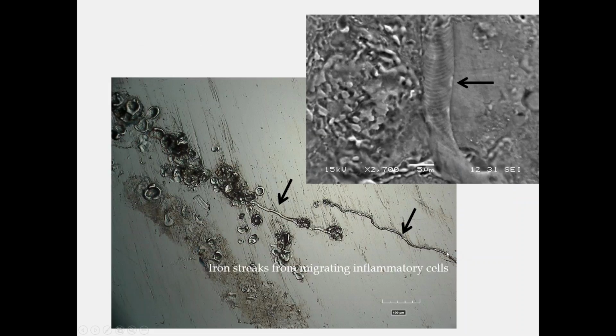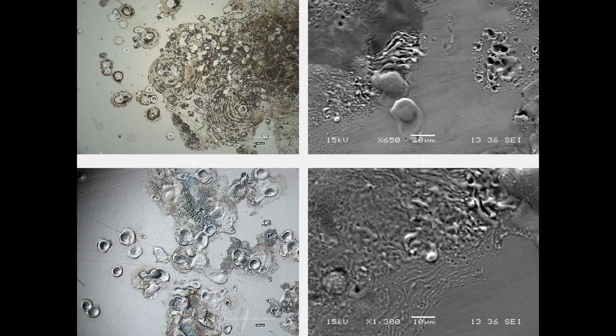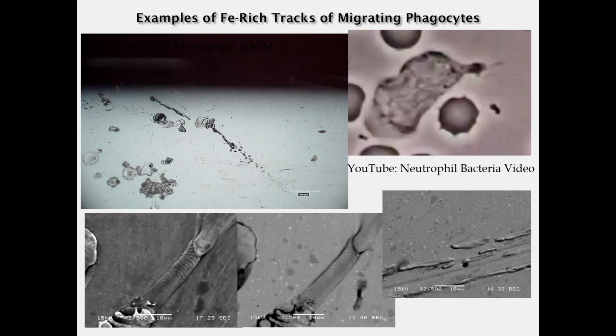In addition, migrating inflammatory cells will leave behind these streaks, which under high magnification look like weld lines. And they are principally made of iron, so we believe iron is the important element driving a so-called Fenton reaction and also inducing this corrosion attack of the cobalt chromium. Some examples of this corrosion attack, both in digital optical micrographs and scanning electron micrographs, show the complex nature of the attack, where there may well be dissolution and re-deposition of ions, as well as dissolution overall on that surface. So these cells are so reactive they are attacking the metal surface. Again, showing you some examples of what we believe are migrating phagocytic cells inducing these damage modes and these iron streaks that are left behind.